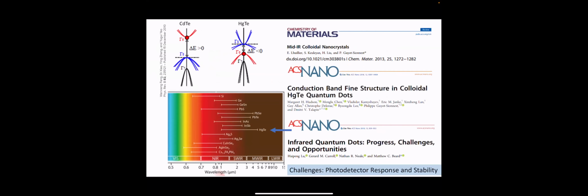Okay, mercury telluride. So here, to go even further into the infrared, mercury telluride is a pretty interesting material. It's a semi-metal, so as a bulk material, it doesn't have a band gap. But when you make quantum dots, you can open up a gap, and you can tune essentially from no gap to pretty far in, not quite to the visible, but here it's shown down the bottom left in this plot is one micron wavelength, so pretty close to the visible.